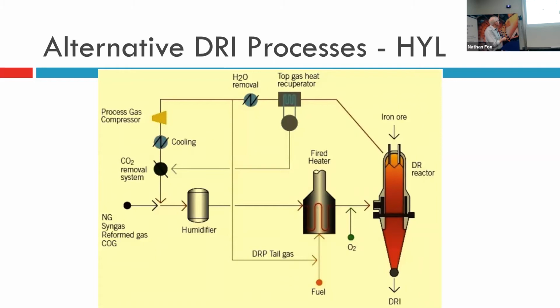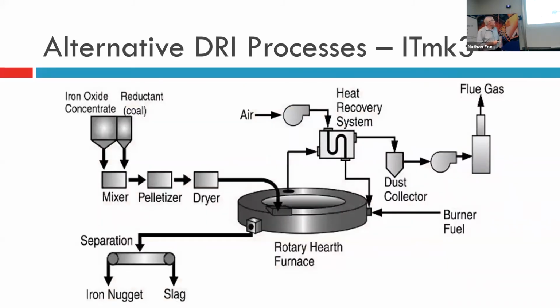There is another process that has been around for about 10 years. It was developed by Kobe Steel and Midrex in Japan and North America, and it uses a different technique. It's called the ITmk3 process. It's almost as if they did some experimentation and got the temperatures wrong, and it accidentally produced a great product. What you do is you mix fine coal with fine iron oxide.